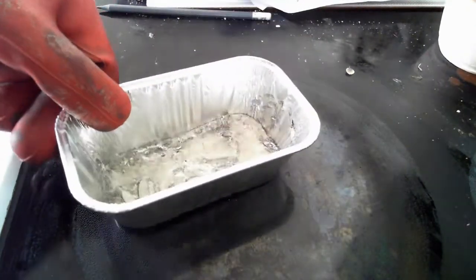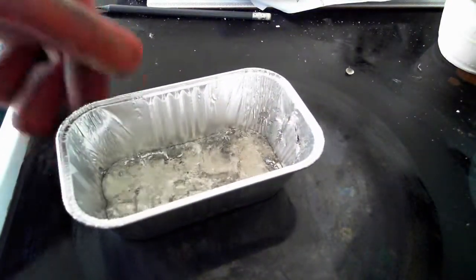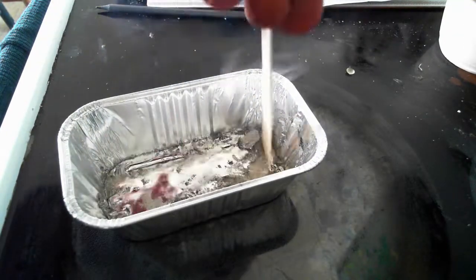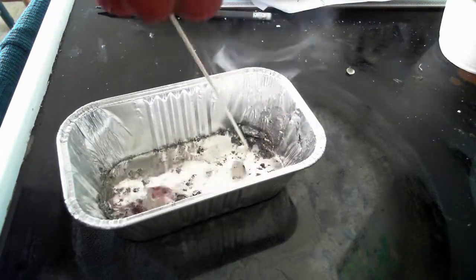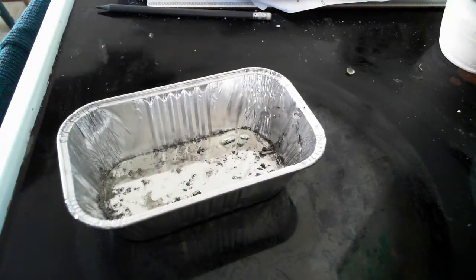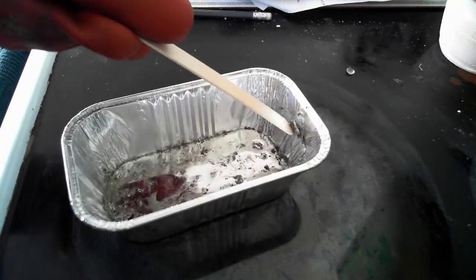You don't want to go anywhere above about 200 degrees Fahrenheit with a metal or any casting material in the impression putty, because it does melt — it will soften. The metal I was using had a little bit of crud on the surfaces, so I'm pulling that out of the liquid metal before I pour it to make a nicer, shinier casting.